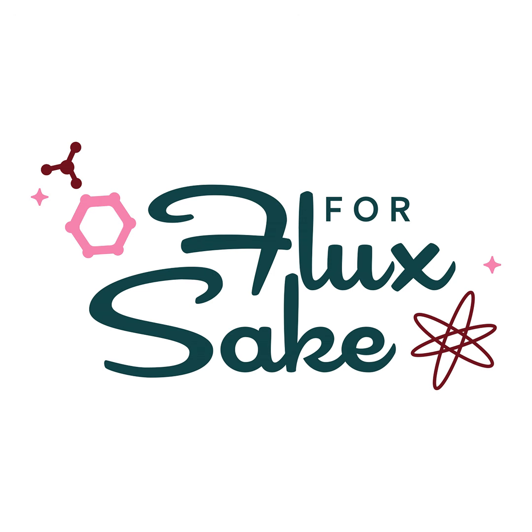Okay. That's craziness. So the reason why you will see some stonewares with higher absorption rates is, I suspect, tied to clay bodies with a ton of grog. If you've got a ton of grog in your clay, that grog will have absorption and pick up water, and you'll often see the absorption rates bottom out at 1 or 2%. And that is what it is. But again, this is why firing curves matter, because you can see how it's maturing and has it hit full maturation. But yeah, it's not a variable in any way.